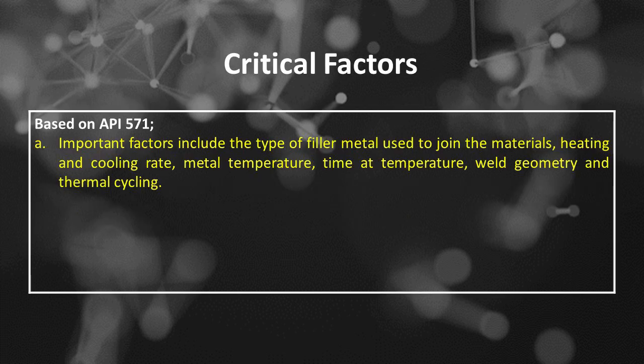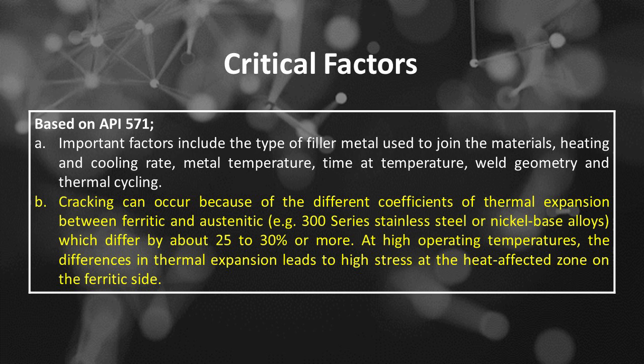Dissimilar metal weld, or DMW, cracking critical factors based on API 571. Important factors include the type of filler metal used to join the materials, heating and cooling rate, metal temperature, time at temperature, weld geometry and thermal cycling. The second is cracking can occur because of the different coefficients of thermal expansion between ferritic and austenitic, such as 300 series stainless steel or nickel base alloys, which differ by about 25 to 30% or more.